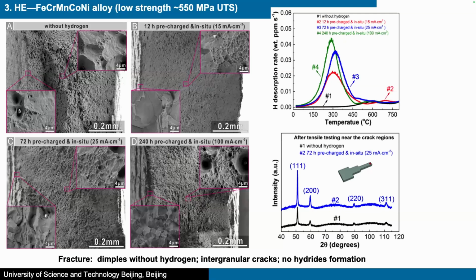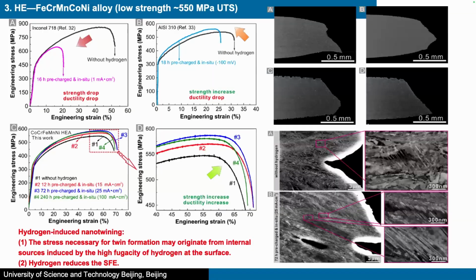We charged for a long time and found that there is no hydride formation during the charging process. These are some of the results, XRD and TDS. We also used ECCI to observe the surface deformation microstructure. We found a lot of hydrogen-enhanced or hydrogen-induced nanotwins during the deformation process. There may be several reasons. First, the stress necessary for twin formation, and also hydrogen can reduce the stacking fault energy of this type of alloy.